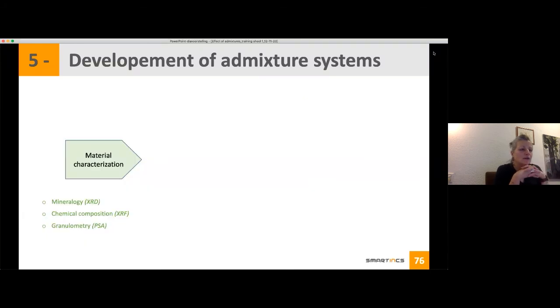So how can we anticipate this type of situation? In the lab, we have a three-phase research. We always start with material characterization. What is the mineralogy with the XRD and what is the composition of my cement? But you can also think, if you have different binders, of your slag or also your fly ash. What is the chemical composition with XRF, X-ray fluorescence? And of course, what is the fineness? Does it change in time or not?